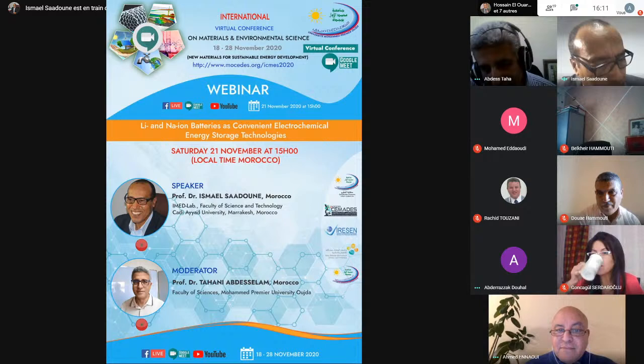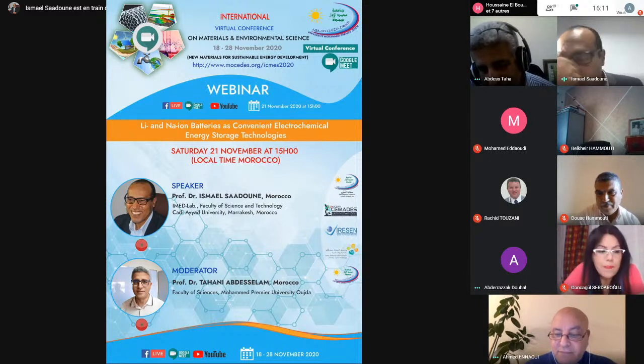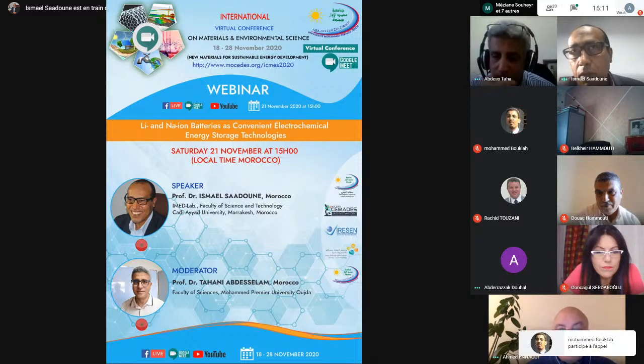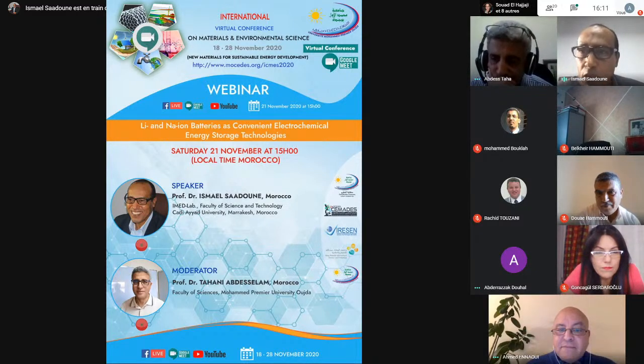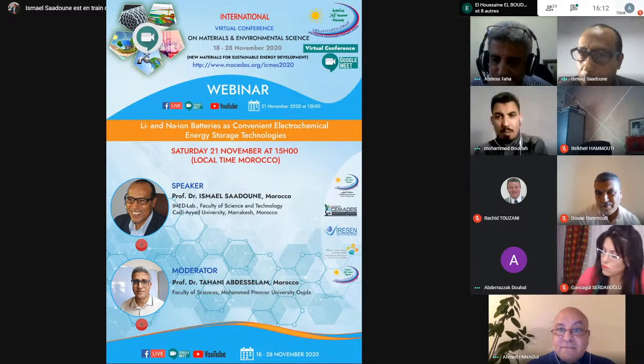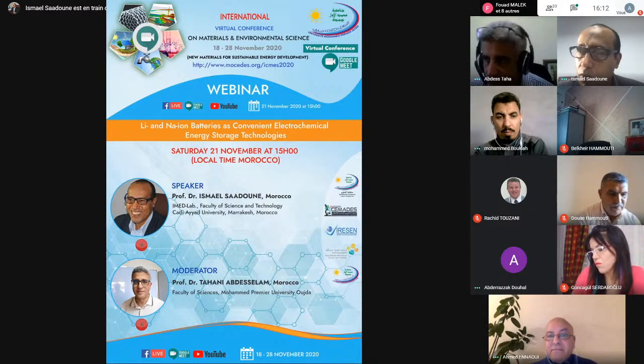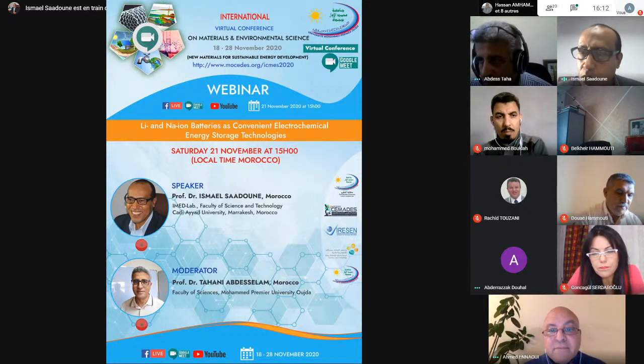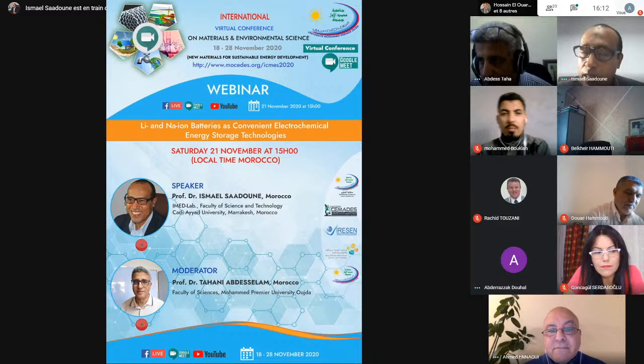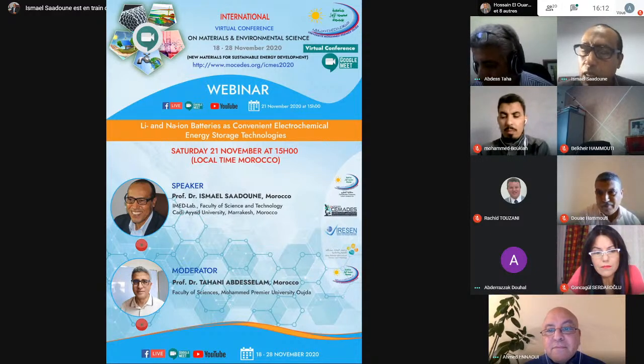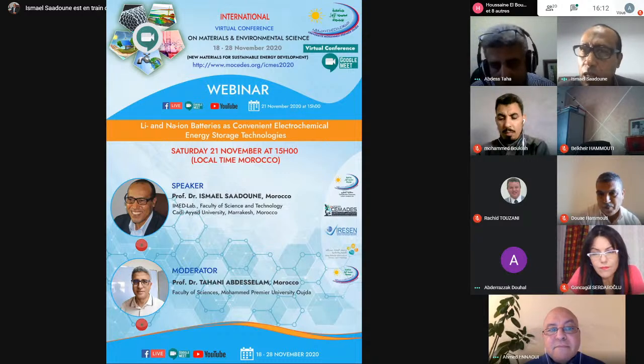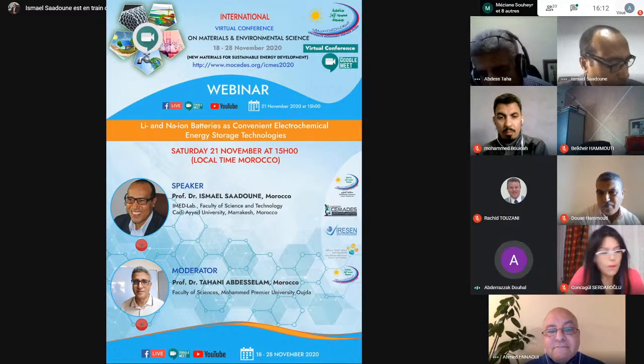Yeah, thank you very much. Yes, the electrolyte now used in the cell is a salt, lithium hexafluorophosphate, LiPF6, dissolved in ethylene carbonate or propylene carbonate or sometimes dimethyl carbonate. It is generally carbonate because of the viscosity, the stability, and so on. But all these solvents are stable only under 4 volt, 4.2 volt. If you go higher in voltage, it doesn't work. You should put some additive, some organic element that stabilizes the structure. But we should keep in mind that we should have good ionic conductivity and good viscosity to be used in real batteries.